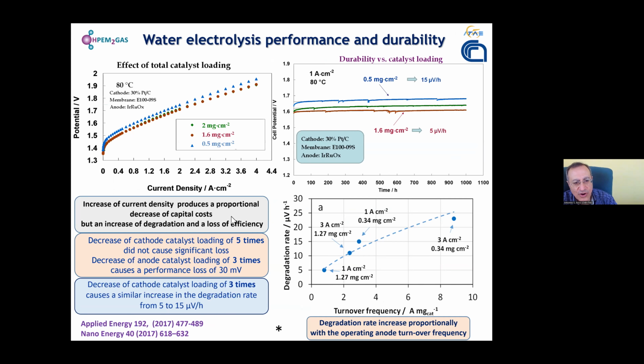The structure of the catalyst is extremely important, but I also mentioned the effect of catalyst loading. If we reduce the catalyst loading, we see some decrease in efficiency, some higher cell voltage, but this is not much. What is more evident is the increase in degradation rate. If we reduce significantly the catalyst loading, we have a strong increase in degradation rate.